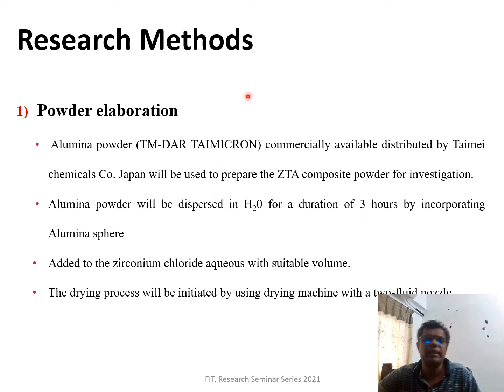Okay, first, the powder elaboration. Alumina powder commercially available from Japan will be used to prepare the ZTA composite powder for investigation. The alumina powder will be dispersed in water for a duration of 3 hours by incorporating alumina spheres. Then zirconium chloride aqueous will be added in a suitable volume. The drying process will be initiated by using a drying machine with a 2 fluid nozzle, to break them into small tiny powder. So we use the drying process.